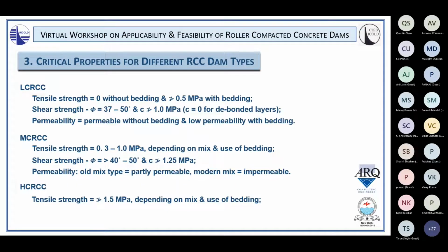The top end, the high cementitious RCC, tensile strength, as mentioned, realistically a maximum of 1.5 MPa, and this will depend again on the mix type, the amount of paste, etc., and the use of bedding. Shear strengths typically between 40 and 50 and even more friction angle, and cohesion of more than 2 MPa. And this type of RCC will be designed generally for impermeability.